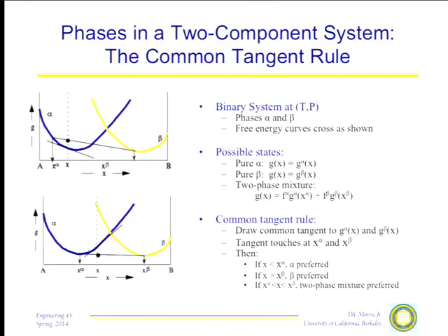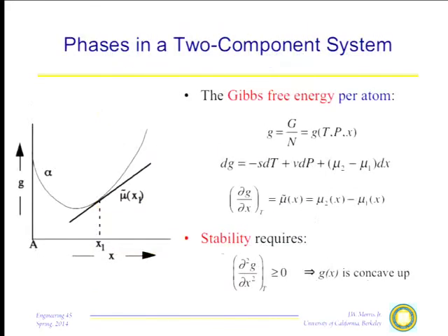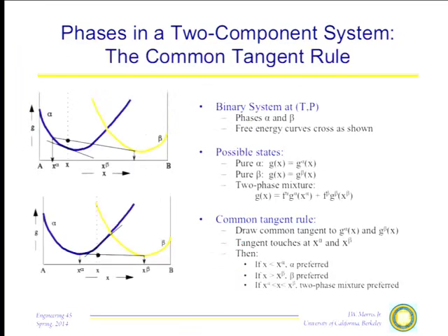It does some other things as well, because the tangent, I guess that's on the previous slide, if I just take the tangent line to the free energy curve, the derivative of G with respect to X at that point, that is the chemical potential of the solution at composition X. So if I come back to the common tangent line, if these two phases, alpha and beta, have the same tangent line, they have the same chemical potential. Now, when we found the condition of chemical equilibrium inside a solution, inside a phase in general, it was that the chemical potential had to be the same everywhere. So this tells me that if I can find a common tangent line between these curves, then the two phases, alpha and beta, at the compositions given by the common tangent line, not only provide a minimum value of the free energy when X is anywhere between X alpha and X beta, but they also give me a situation in which these two phases are in chemical equilibrium with one another. So this is the equilibrium situation here.